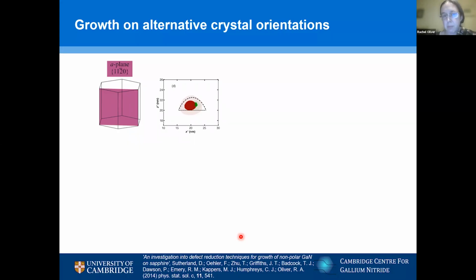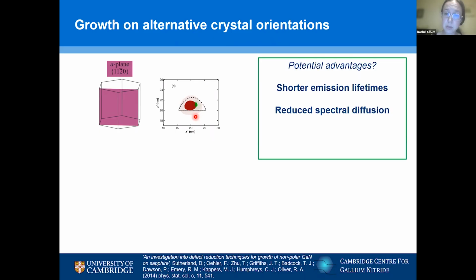So how might we get rid of the spectral wandering? Well, the internal electric fields tend to be along this c-axis, along the long axis of my hexagon. If we go at 90 degrees to that, in a quantum well, we'd actually completely eliminate the internal fields. For a quantum dot, we've still got an in-plane c-axis, which is left to right in my diagram here. And that means we will still have interfaces which are at least at some acute angle to that c-axis, and we'll still see some in-plane separation of the electron and hole. But we should theoretically be able to bring the electron and hole much, much closer together in this case. Bringing the electron and hole together should reduce the emission lifetime, and it should also reduce the spectral diffusion.